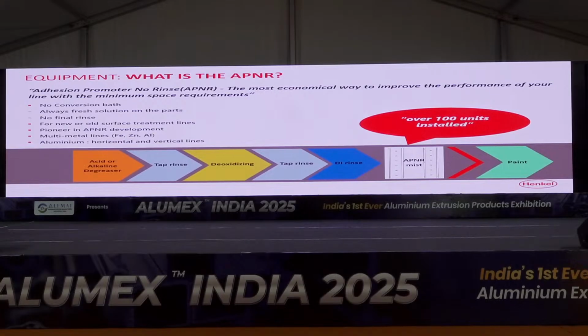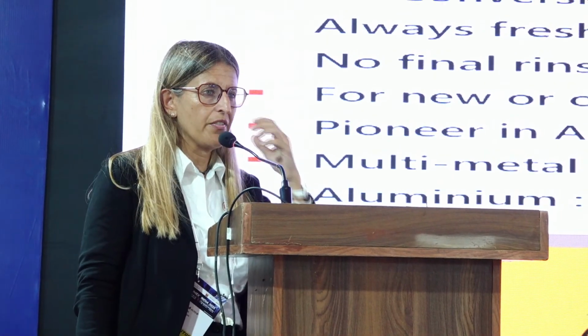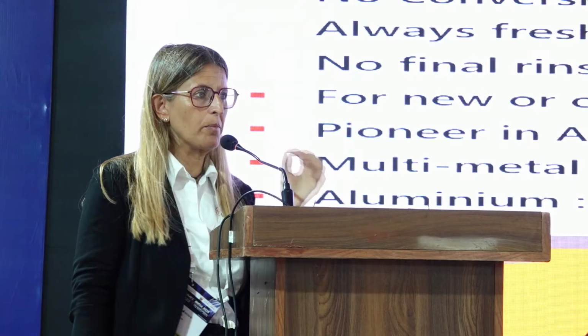This is really useful, for example, for customers that are working with Chrome 6 and want to change to a non-Chrome 6 system. Why is it important? Because to get rid of Chrome 6, if you've been working with Chrome 6 for so many years, in these Chrome-free products, 1 ppm of Chrome is a pollutant. So you can damage the non-chromium product, the process itself. So if you install this APNR at the end of the system, you create the non-chromium process without any problem and any fear that the material will be contaminated by Chrome 6.